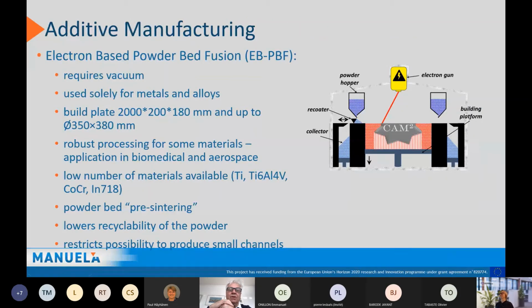EBM is a different story. As you know, EBM, or electron-based powder bed fusion, also called electron beam melting, is the first starter coming from Arcam GE Additive. It requires vacuum, of course. It's only metals and alloys. You see something on the build plate, quite decent sizes. There's some range of materials, rather robust, particularly for applications in biomedical and aerospace, and we have it inside Manuela. You see titanium, TI64, cobalt chrome. As you know, here you do pre-sintering on the powder bed. So the powder bed itself is an anchoring, not just a support structure. That means there's a little bit less recyclability of the powder. And since you do it like this, there are not necessarily exactly the same design possibilities to create small channels, for example. So you could say the laser technology and the electron-based technology have different pros and cons, right?